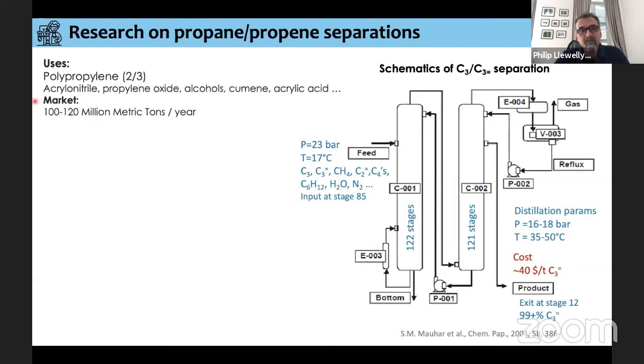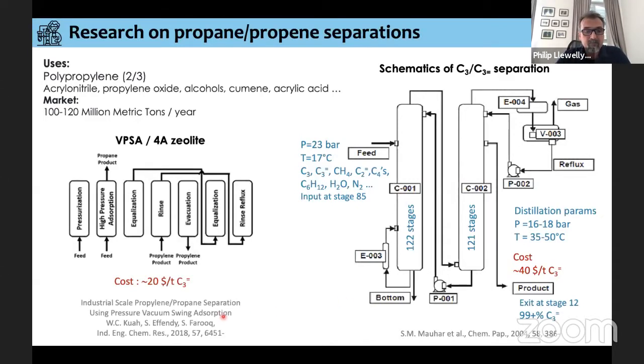And the cost of this separation is around $40 per ton of propylene. Which, if you come back to this market size in millions of metric tons per year, is a huge amount of money used for the separation. Now, in terms of research, Farooq and his group in Singapore have suggested the use of, for example, a 4A zeolite with a vacuum pressure swing adsorption system with 7 steps here. And they suggest that the costing is almost half of what we see in this industrial zone. So if we move to an adsorption separation with respect to distillation, we could potentially save around $2 billion, which you can imagine would also mean energy savings.